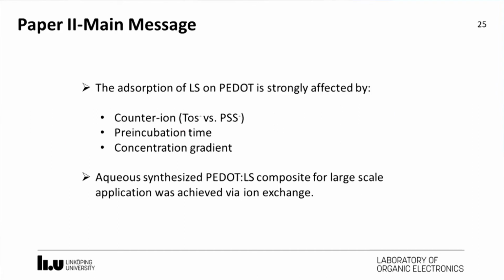So in this paper, we studied the adsorption of lignin sulfonate on PEDOT and found that it's strongly affected by the counter ions. It's affected by the pre-incubation time. It's also an automatic, spontaneous process due to concentration gradient. We have also optimized the synthesis route in aqueous solution to get the PEDOT:lignin sulfonate composite via ion exchange, and that is good for large-scale application.